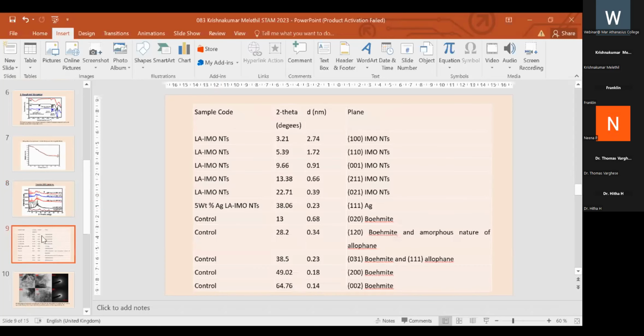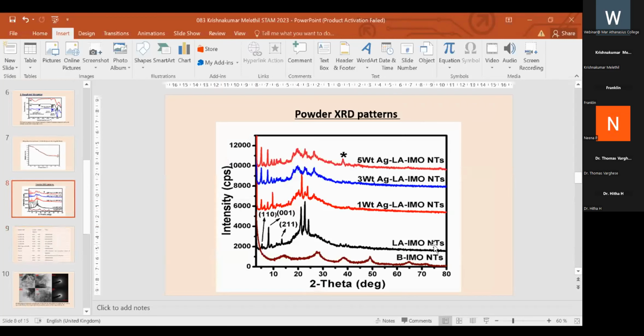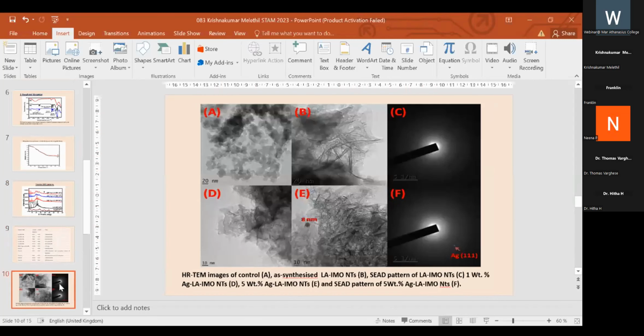So it's the 100 plane. This is the explanation of the XRD peaks of imogolite nanotubes. And the interesting thing is, we can observe the silver phase appearing at 5 weight percentage Ag-LA-IMO-NTs. That is also underlined by the TEM images.